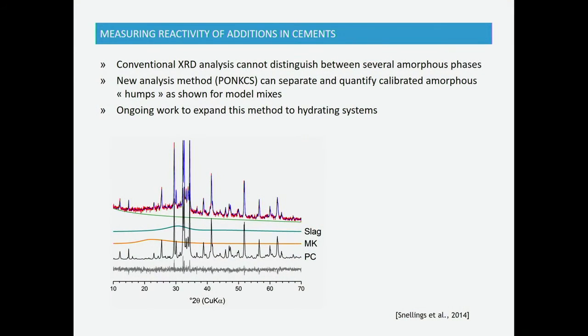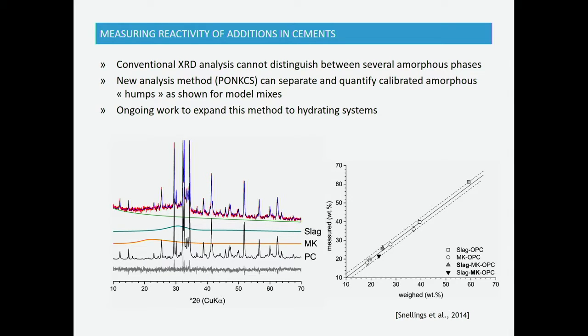Another development was in the field of X-ray diffraction. As has been mentioned before, conventional XRD analysis makes it not possible to distinguish between different kinds of amorphous materials. There is a new analysis method out there, and we tried it for instance on anhydrous systems, and we're also developing it now for hydrating systems, in which you can actually separate contributions, for instance, of slag and metakaolin in a blended cement, and this works pretty well. For instance, here, this is for anhydrous mixes. You can have quite a good correlation between what you measure and what you weigh out. So also here, we think that considerable progress is possible in assessing and characterizing these materials and also knowing how they react. Of course, both of these developments can be done only in research labs.